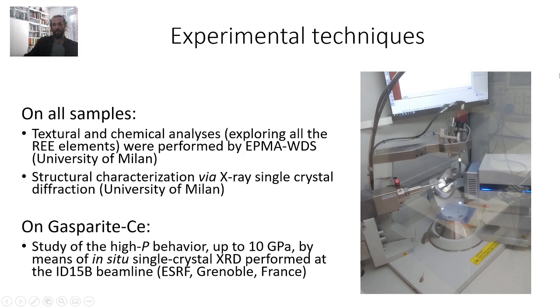For all the samples, the chemical composition has been determined by electron probe microanalysis in wavelength dispersion mode, whereas the crystal structure of all the samples has been determined on the basis of X-ray single crystal diffraction data collected at the Earth Science Department of the University of Milan. Up to now, only on gasparite has the high pressure behavior been studied, by means of in situ single crystal X-ray diffraction performed up to 10 gigapascal at the ID15B beamline at the European synchrotron ESRF.